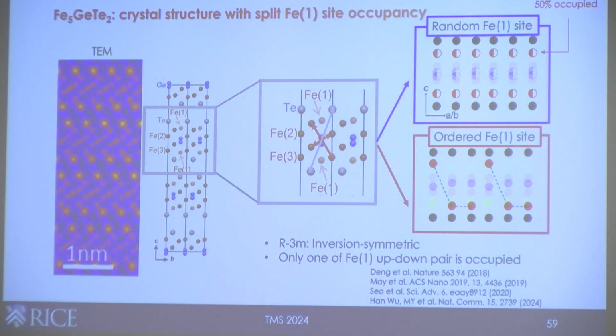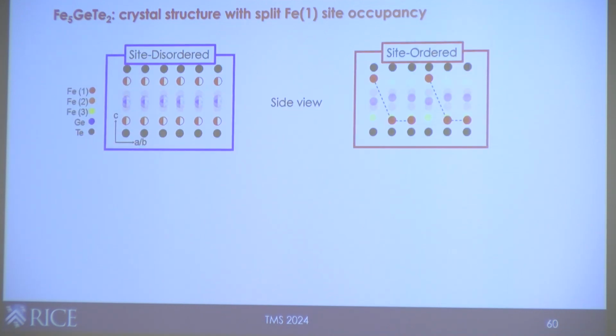The other stable structure, it turns out, is that the crystal likes to choose these sites in an orderly fashion. It goes like up, down, and so on and so forth. Right, and this one obviously breaks inversion symmetry, so these have different symmetries, but they have the same number of occupied sites per unit cell. Okay, so why am I telling you this? Thank you for bearing with me for that slide.